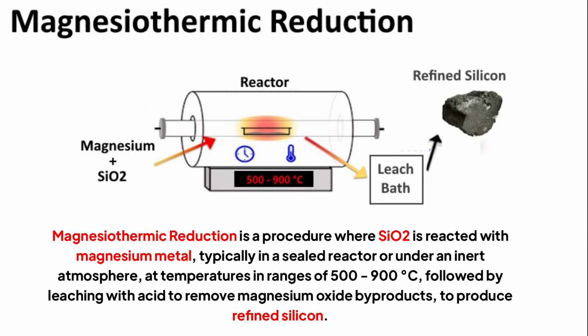Magnesiothermic reduction is a procedure where SiO2 is reacted with magnesium metal, typically in a sealed reactor or under an inert atmosphere, at temperatures in ranges of 500 to 900 degrees Celsius, followed by leaching with acid to remove magnesium oxide byproducts, to produce refined silicon.